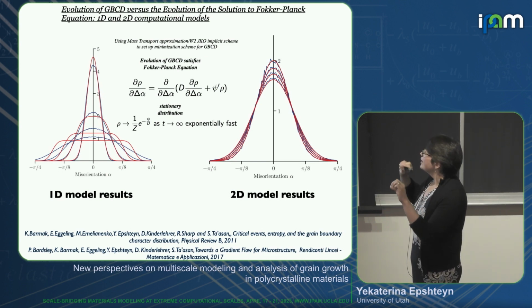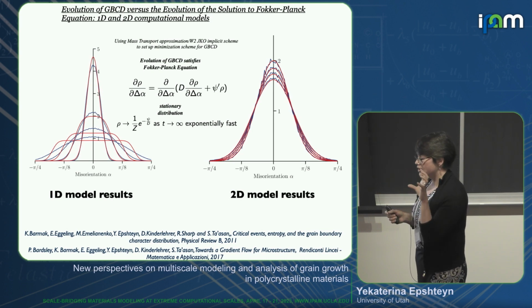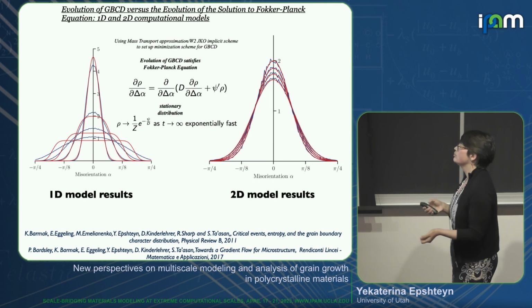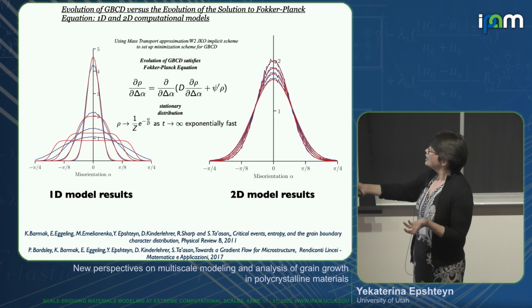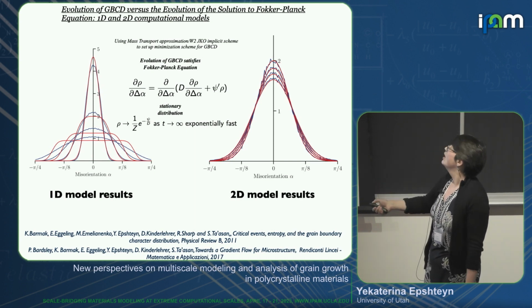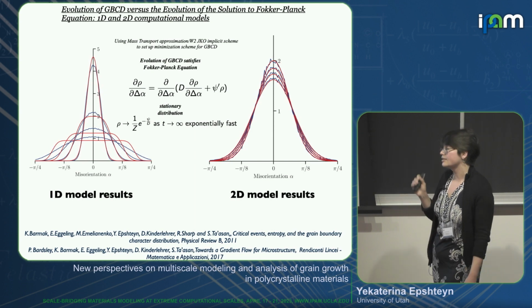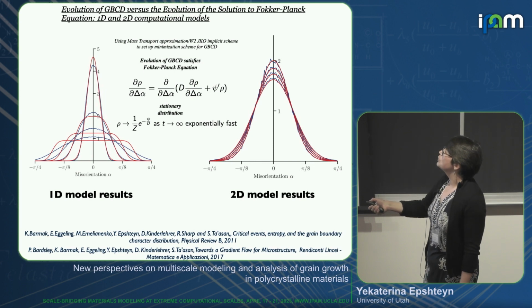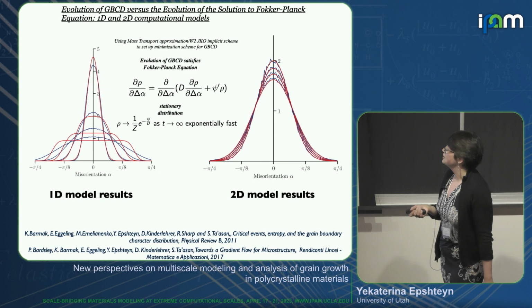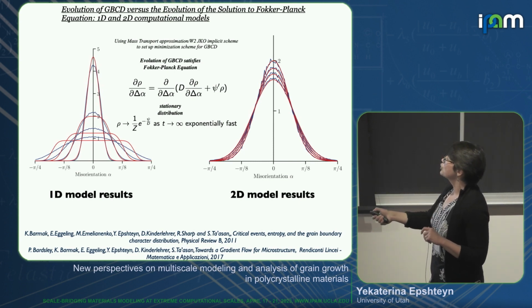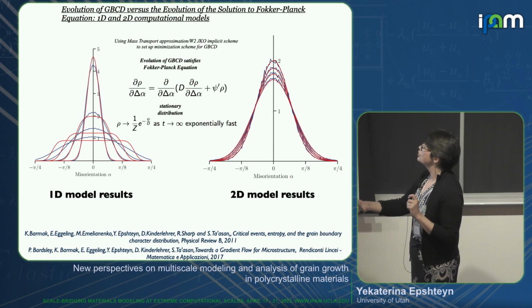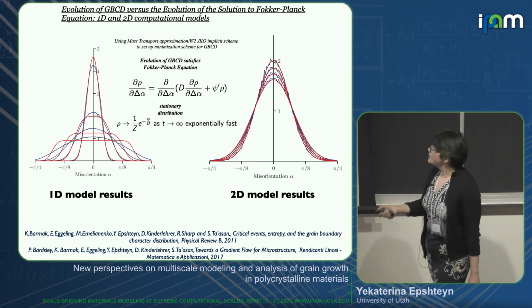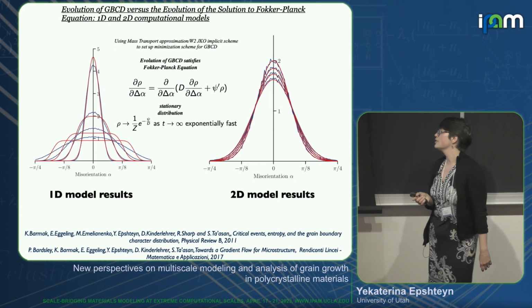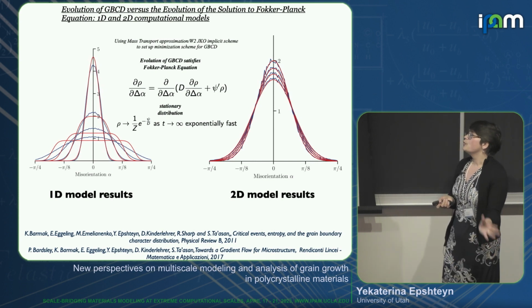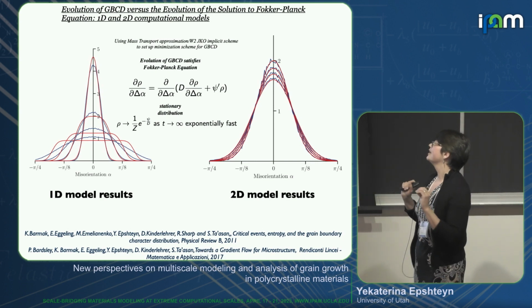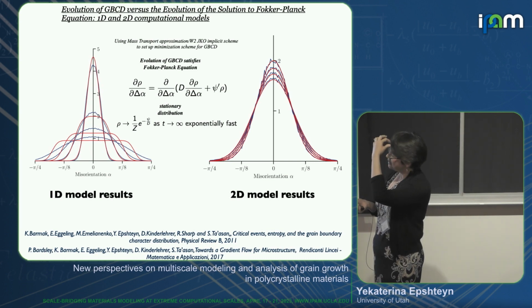But using that idea of removing curvature effects and just focusing on what happens at triple junctions and misorientations, and with the help of mass transport approximation, namely the Wasserstein two implicit Jordan, Kinderlehrer, Otto implicit scheme, we were able to set up a minimization scheme for grain boundary character distribution. And using that idea, we were able to show that GBCD indeed evolves as a solution to this Fokker-Planck equation. And as a consequence of that, the steady state is given by a Boltzmann distribution for grain boundary energy density. So that theory was developed for the reduced 1D model where triple junctions were not exactly even triple junctions.